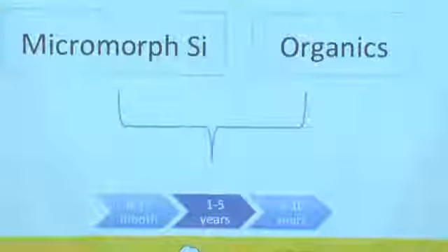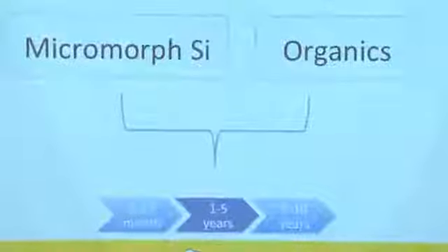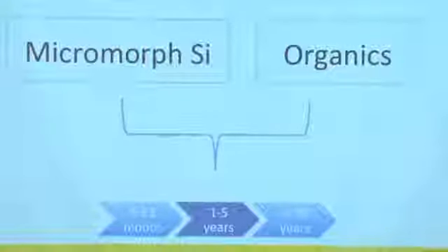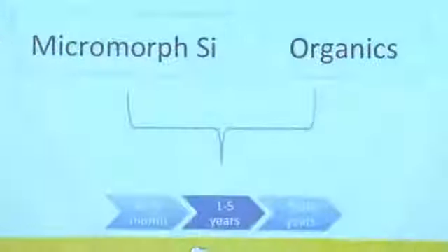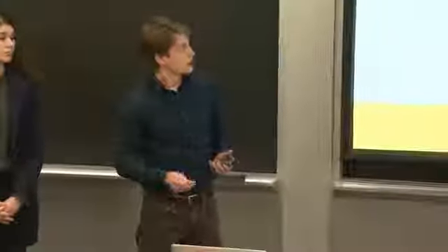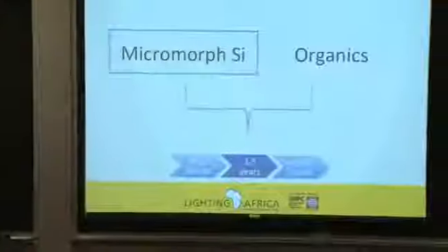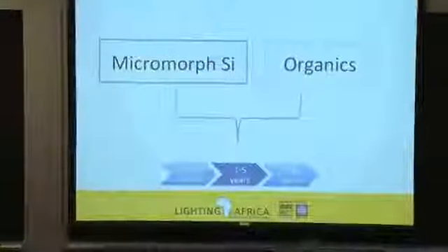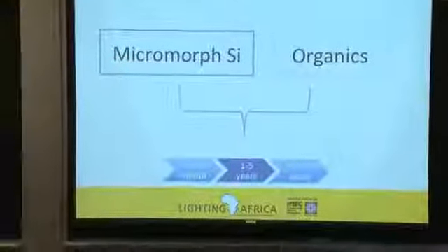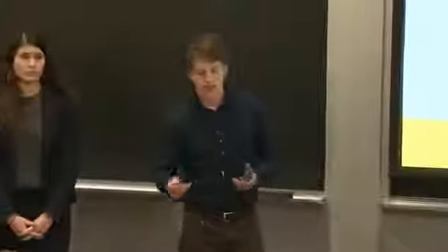You might wonder why we didn't include CdTe or CIGS. The reason is because since they contain cadmium, they have to be recycled at the end of their life, and we didn't think that was very realistic in this context. So first, I'll talk about micromorph silicon, and this is a tandem thin film cell with amorphous silicon and microcrystalline silicon. It's on the verge of commercialization within the next few years. Cost estimates are about 70 cents a watt, and efficiency estimates are about 10%.